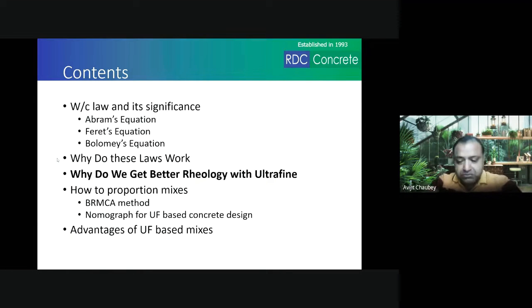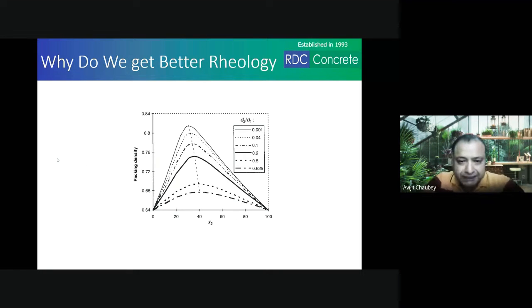Now, ultrafine materials basically give you many advantages. The first advantage is it gives you a better rheology. The ultrafine materials give you better rheology as compared to materials without ultrafine. And this is what has happened in modern science. So, as I told you, Francois de Larrard has done a lot of studies in particle packing, and he has burst some of the myths in concrete technology. The first myth in concrete technology is that uniform gradation of aggregates gives you good particle packing, which is absolutely wrong. What is uniform particle packing?